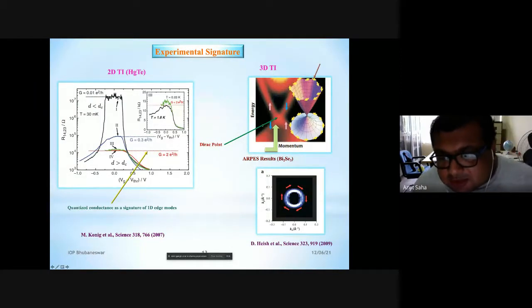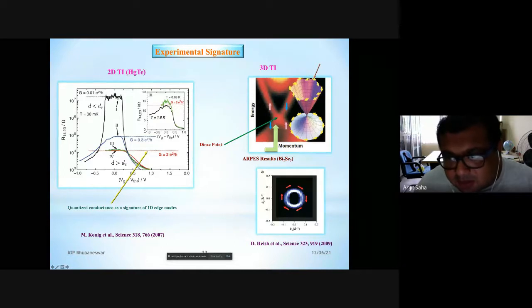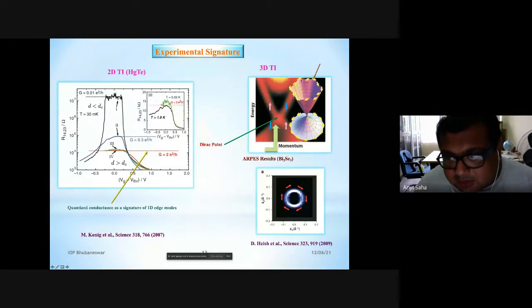And also in the three-dimensional case, they performed angle resolved photoemission spectroscopy, and they have shown the Dirac nature of the surface modes here. In this picture you can see that on the surfaces your spin and momentum are actually locked. So you will get a spin texture here, because spin and momentum follow the Dirac cone and behave like this. And this spin texture you can also see in the planar picture in experiment. They also show this in the Fermi surface. You have the spin momentum locked motion of the electron.